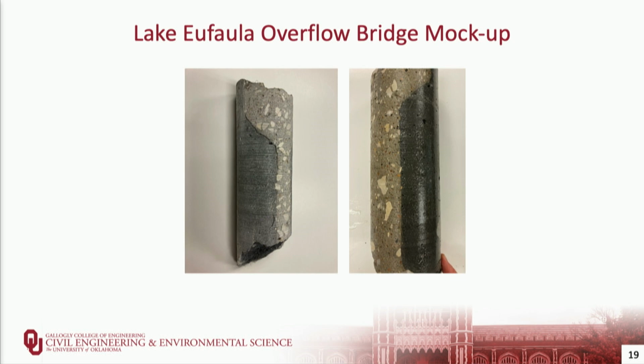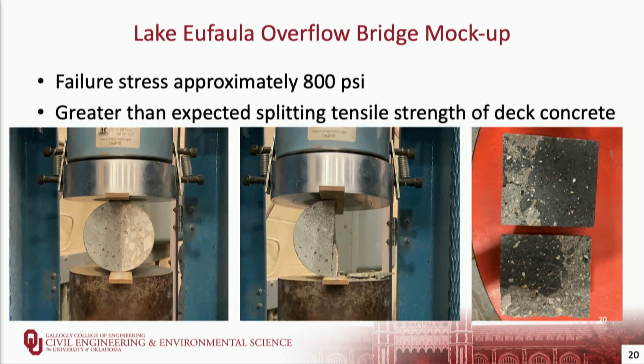We also, like I said, took some cores from the interface between the panel and the UHPC joint. We were able to get some that were very close to right in the middle that we could then cut down. So the one on the right, we actually cut down and ran a splitting tensile strength test on that core that had half the UHPC, half conventional concrete to examine the bond between the two. This specimen failed at about 800 PSI. It was hard to tell exactly because in the middle picture, that half UHPC core is still holding the same load as at the point that it cracked. So to put that in context, the expected splitting tensile strength for the concrete in the panels was only 500 or 600 PSI, so that the UHPC provided a bond that was equal to or better than the strength of the concrete itself.